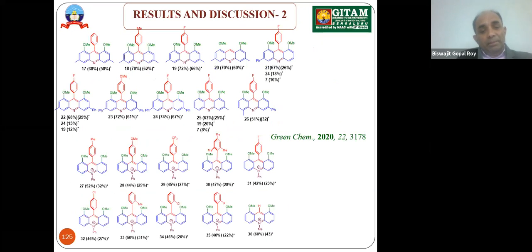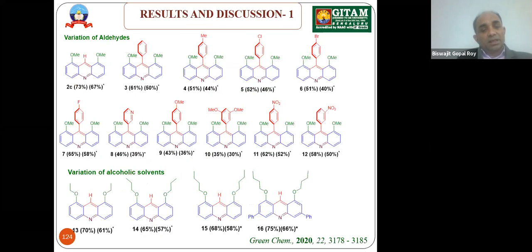Please go back. Yes, when we use different alcohols as the solvent, the alcohol gets incorporated into the system. So here initially methanol, then ethanol, propanol, and butanol, all got incorporated into the system, and that doesn't change the yield much. But when there is a substitution in the diketone, the yield also increases. Next slide, please.